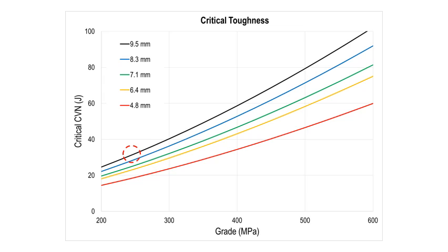When you look at the GEM model, the GEM model differentiates between whether you have a crack and whether you have a metal loss flaw, and the change there comes into play. You would use a different gamma exponent if you were to look at metal loss itself. So I'm not recommending doing a metal loss calculation. I'm just demonstrating that under these conditions, the fracture term falls out of the equation. So grade B, 9.5 millimeter pipe, if you've got better than 30 joules worth of toughness, then the fracture term essentially falls out of the equation.